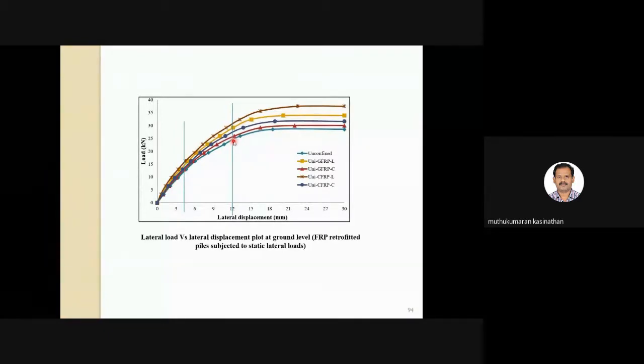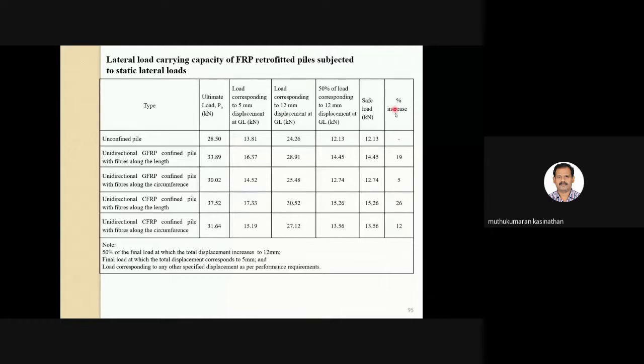Where the piles are on the verge of failure, we want to bring back the capacity of the pile. For that, we have used the FRP. We have wrapped the FRP so that somehow we are able to bring back the capacity. You can see the capacity of the pile. Look at here. This is the actual capacity of the original pile, without any distress. These piles we loaded up to 85% of the ultimate load, then we did the retrofitting using FRP. Then we applied the load and we got the response. Look at here, these loads are almost slightly better than the conventional, unconfined, original pile. So this is what our intention is.